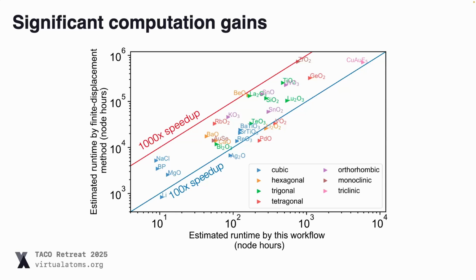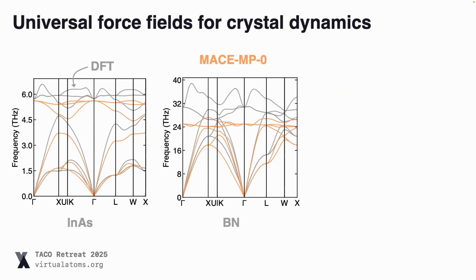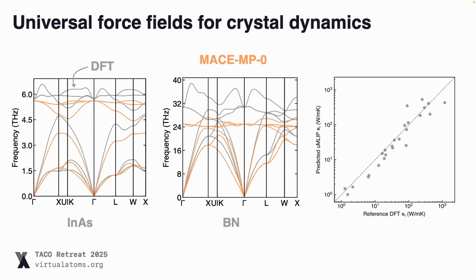I guess at this point, it would be remiss not to say that there's an even easier way to get computational speed up for these materials, and that's towards using machine-learned force fields. I'm not going to talk too much about this, but one thing we've been looking at is these universal force fields. The issue is that when you use a universal force field, you get this considerable systematic underestimation of the phonon frequencies. And people are trying to account for this, but in most cases, it's still there. So this is looking at MACE-MP-0. This is just for indium arsenide and boron nitride. You can see compared to the dashed grey line, the DFT, MACE is considerably lower. And when you go on and calculate the lattice thermal conductivity for these systems, you see quite a considerable spread in the lattice thermal conductivity.